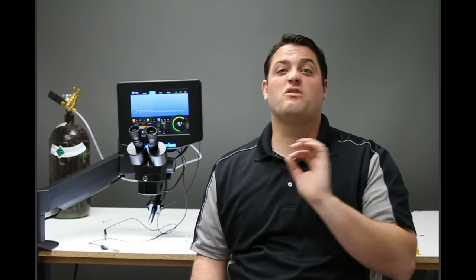It's very important to keep in mind that the higher the zinc content, the more of that blackness and soot you're going to get, and it's going to give you a more and more poor weld. That is more applicable to brass specifically, because there tends to be a higher zinc content in brass. But certain silvers certainly have a high zinc content, so be aware of that. If you're working with argentium, sterling or fine silver, you will notice very little difference between the three in the welding process, simply a little bit more blackness on the weld. But the type of silver is very important.